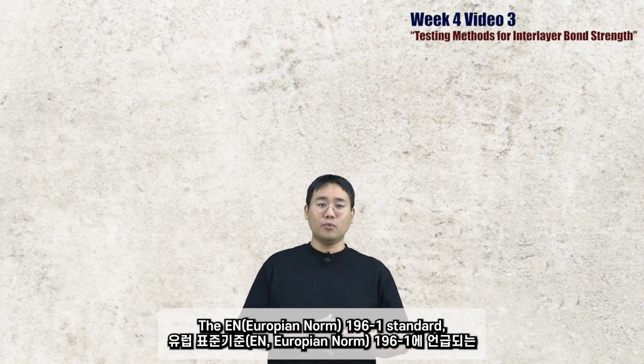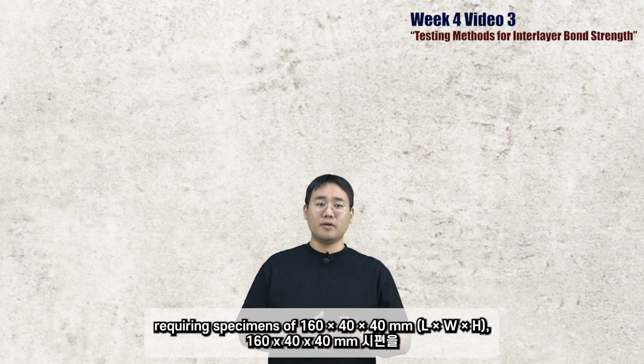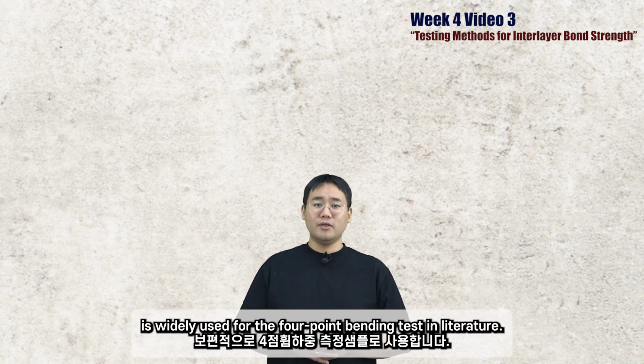The European norm 196-1 standard, requiring specimens of 160 millimeters in length and 40 millimeters in cross section, is widely used for 4-point bending tests in literature.